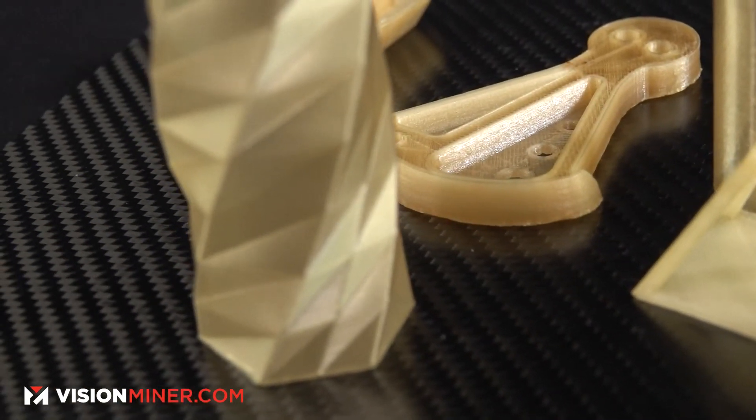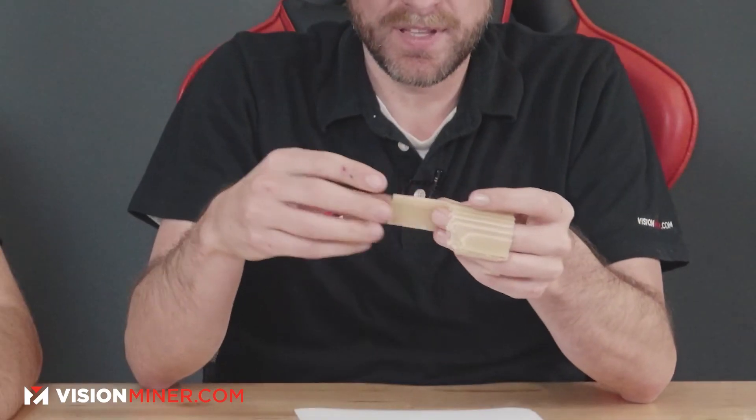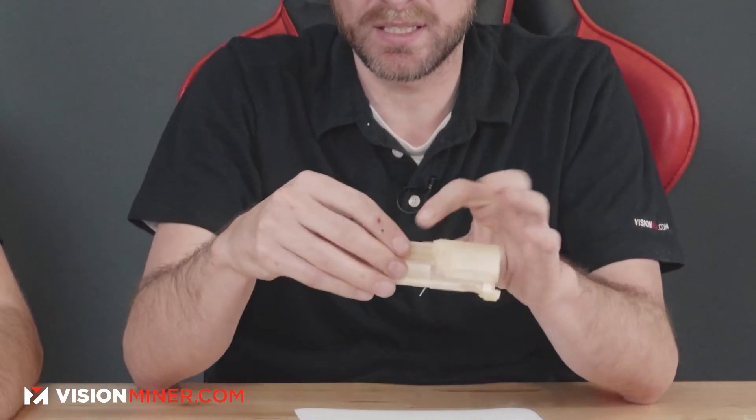The support material handles really well — it's flexible and strong. It printed with simplified support structure. For print settings: nozzle temperature runs 360 to 390 Celsius. You want to crank the bed as high as possible — we like 160 Celsius — and push your chamber temperature as high as possible too. 90°C or above provides good results. For really complex geometries with many islands, you want the hottest chamber possible to avoid warping and curling.